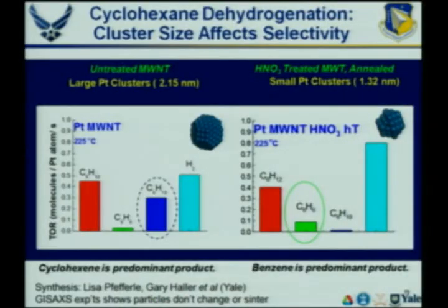Already starting to transition. So this MURI group includes people at Yale doing the synthesis, Lisa Pfefferle, Gary Haller, some folks at Tufts I'll mention, people using facilities at Argonne, using X-ray scattering at Argonne, to show that in the course of these experiments, these catalysts don't sinter. One of the interesting and kind of insidious things about catalysts is that you can put something in, the reaction takes place, the catalyst changes structure, it sinters, it changes morphology. Then when the reaction's done, it goes back to its original form.